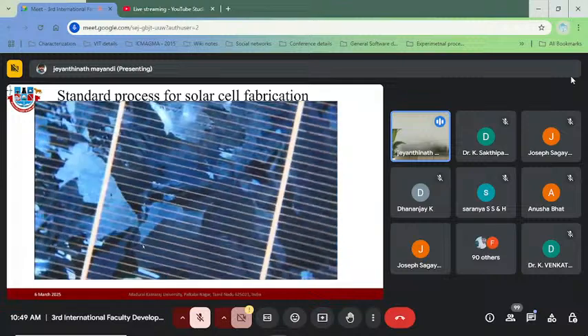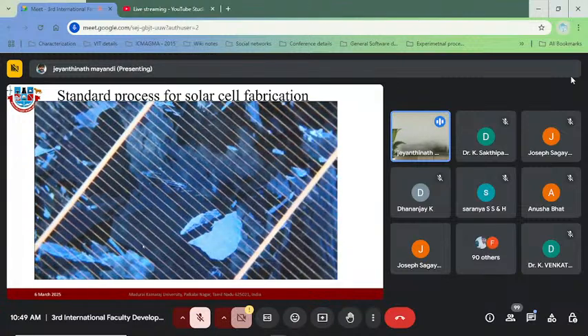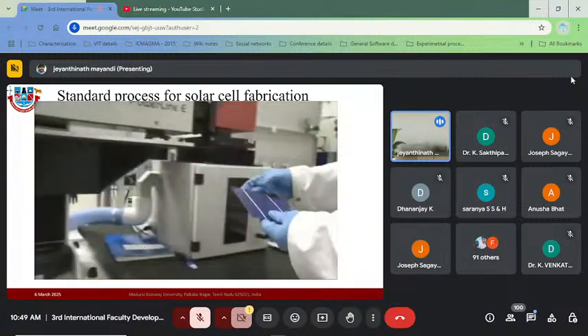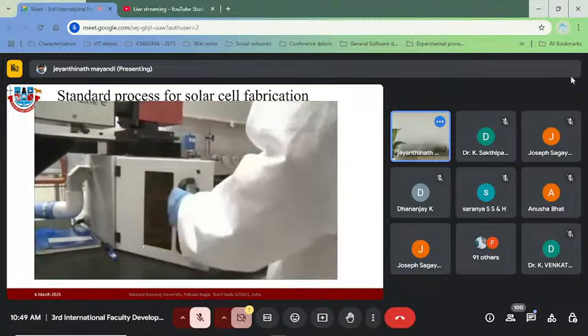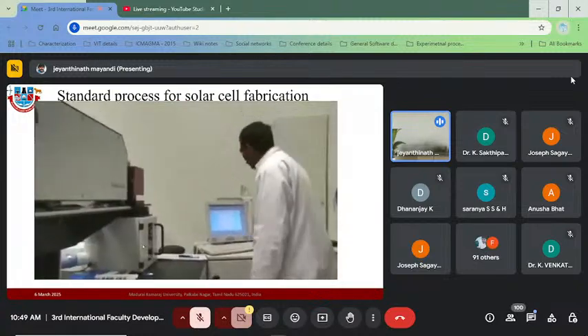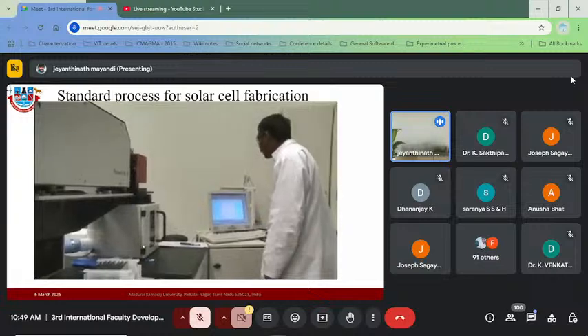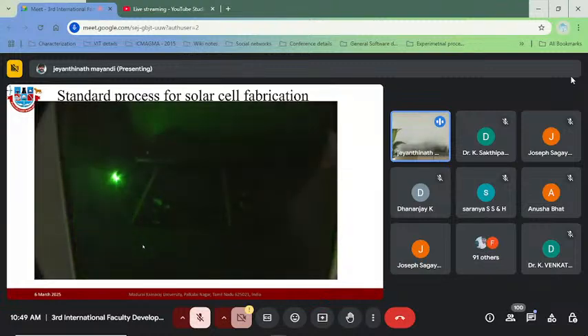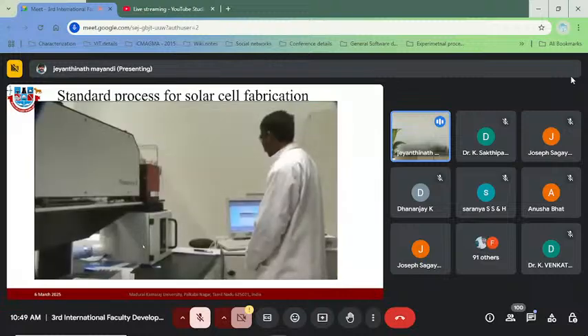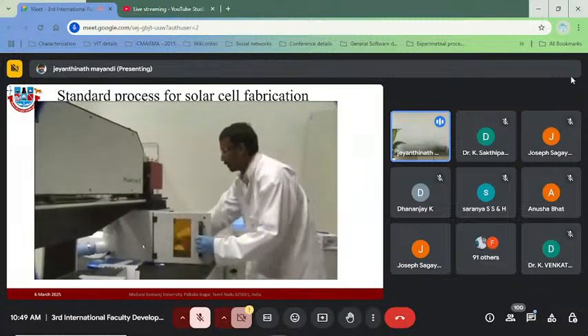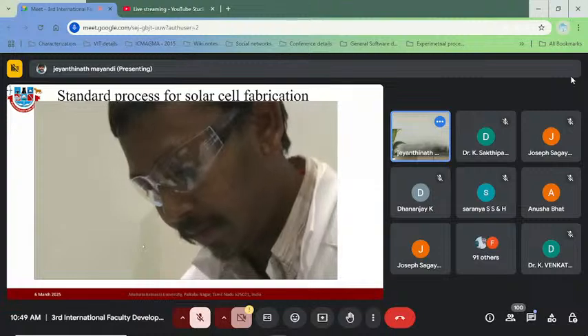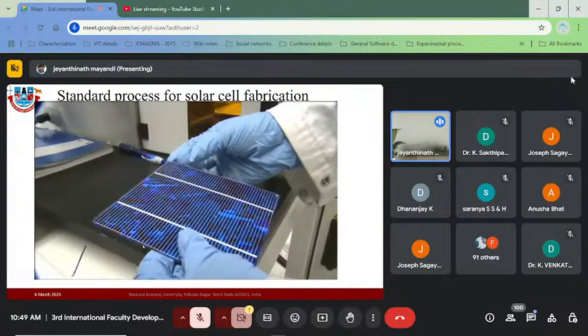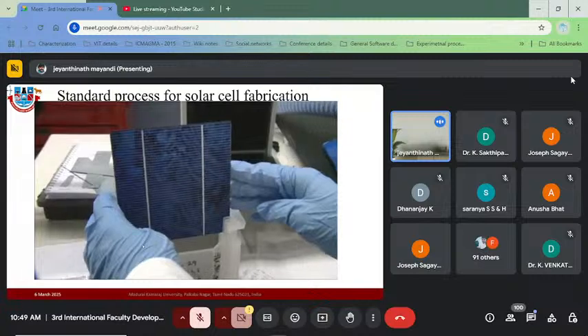The solar cell is nearing completion, but we still don't have full control over the excited electrons. To ensure that the electrons don't take shortcuts and create short circuits between the front and back contacts, an isolating trench is made along the edge with a laser, a so-called edge isolation. Now the solar cell is in principle finished.